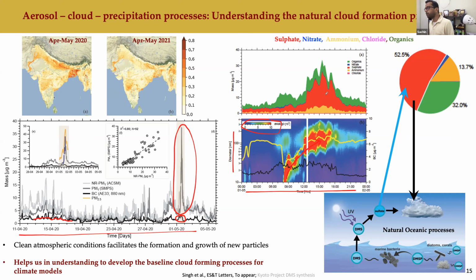So when we looked into the chemistry for this particular period, we made a pie chart, and we found that almost 53% was sulfate. This is extremely unheard of: when you don't have anthropogenic activity, where does this sulfate come from? So we took this chemistry and physics and put it into different thermodynamic models. What it told us is that marine bacteria release DMS, dimethyl sulfide. This dimethyl sulfide undergoes a very complex reaction to give you H2SO4 through MSA, methanesulfonic acid. Generally, when you have a high concentration of aerosols, this MSA or H2SO4 condenses on the pre-existing particles. But since the anthropogenic level was very low, that gave them an opportunity to nucleate themselves and form pure sulfate particles.